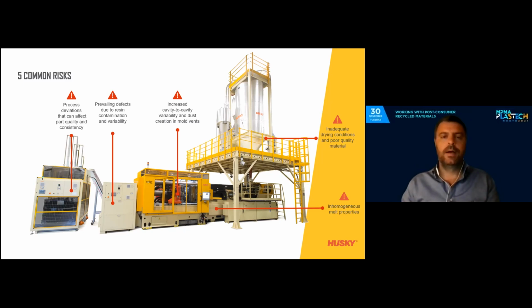Also, when we mix two materials, this can lead to inhomogeneous melt properties. And there's also an increased cavity to cavity variability, and the possibility of dust creation in the mold vents. And also, if the material quality is in reality low and we have a huge quantity of contaminations or black specks, those will pass through in the system, and there may be prevailing defects on your preform. And then, of course, we need to have a system that is capable of handling process deviations that can affect the part quality and consistency.